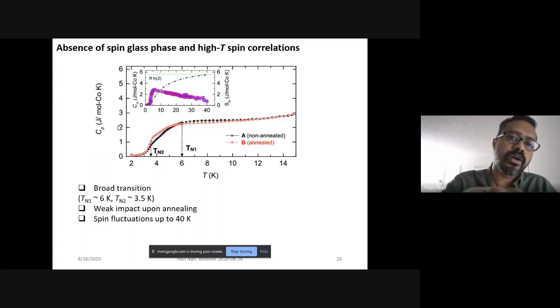Why did I take R log 2? Because it's a spin half system. So the total magnetic entropy should level off at R log (2s plus 1). That doesn't happen at the temperatures where the phase transition occurs, which is below 10 Kelvin. It happens only at 40 Kelvin.